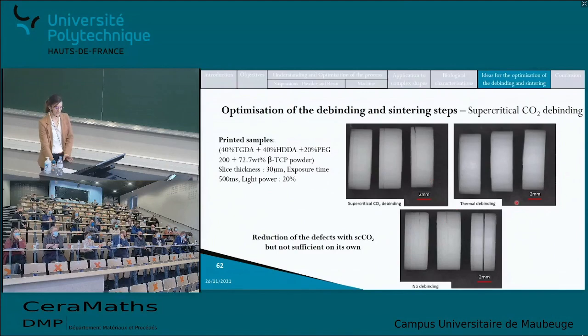However, it seems that there is less delamination when the supercritical CO2 is used than when no debinding at all is used. So the supercritical CO2 could help to ease the debinding, but cannot be used on its own. So the idea was to combine it with microwave sintering and debinding steps.